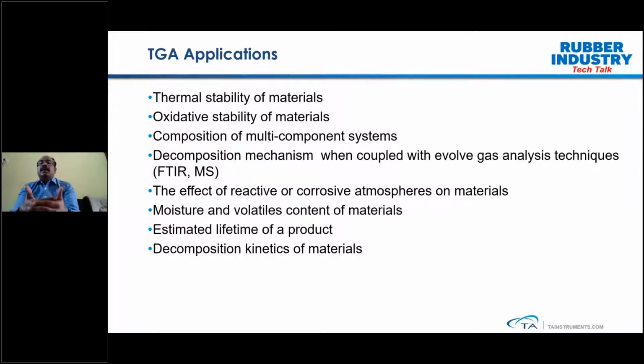As we heat the sample, the components start to evolve one by one. That can also be coupled with evolved gas analysis techniques. In this case, we couple the TGA with either FTIR or mass spec, and that gives further information on what type of evolved gas is coming out. This also gives a clear understanding of the decomposition byproducts evolving from the sample, and many times it helps us identify the polymers. So if you want a better understanding of what is coming out of the sample, you can use TGA with evolved gas analysis.